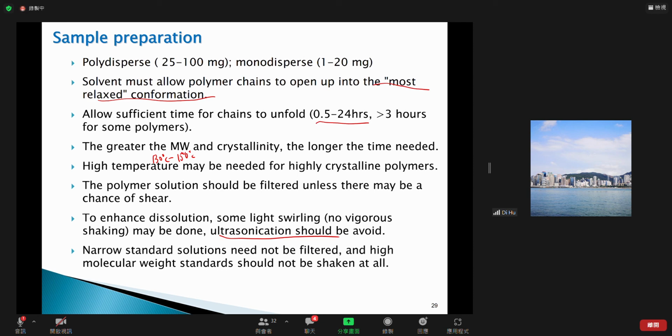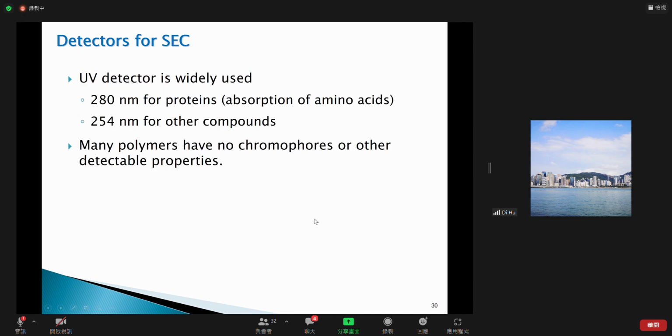Normally we use THF for polymers. For polyamides and esters, you can use a somewhat more polar solvent, such as cresol, and you can generally heat it at maybe 90 degrees C, which should be fine. That's something to mention about it.